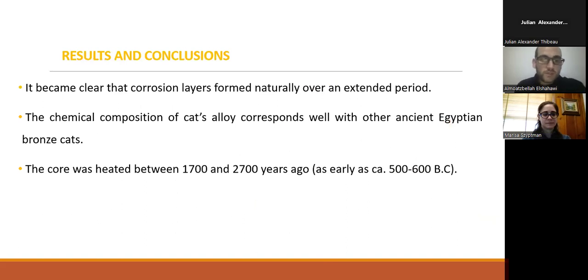So, as for the results and conclusions, through the investigation of the interior surface using digital microscopy, it became clear that the corrosion layers formed naturally over an extended period. The chemical composition of the cat's alloy corresponds well with other ancient Egyptian bronze cats according to portable XRF results. The TL results indicate the core was heated between 1,700 and 2,700 years ago.